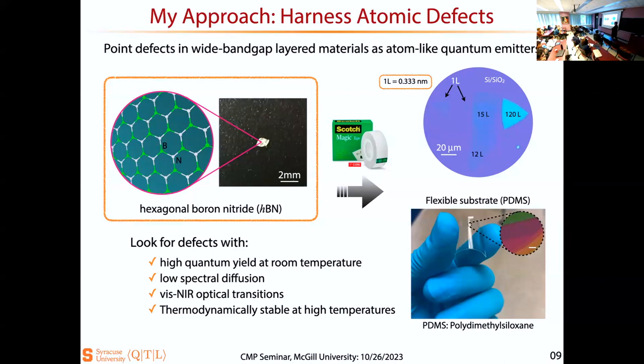Because our growth process was not clean enough, the sample was already dirty. So why do we still work with the CVD growth sample? Because then you have very precise control layer by layer. We can grow one layer, two layers, three layers, four layers. So if you find a color center, you very precisely know where it is. But for the single crystalline sample, we don't know. That was one of the fundamental important questions which we proposed how to solve, and also solved. I'm going to show that result.